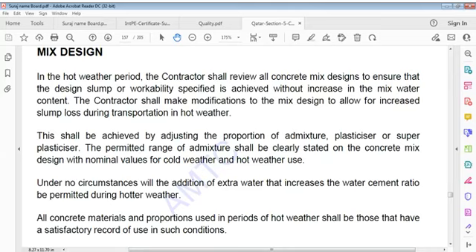Of course, preparations: mix design. In hot weather period, contractors shall review all concrete mix designs to ensure the design slump or workability specified is achieved without increase in mixed water content. Contractors shall make modifications to mix design to allow for increased slump loss during transportation in hot weather. This shall be achieved by adjusting proportion of admixture.